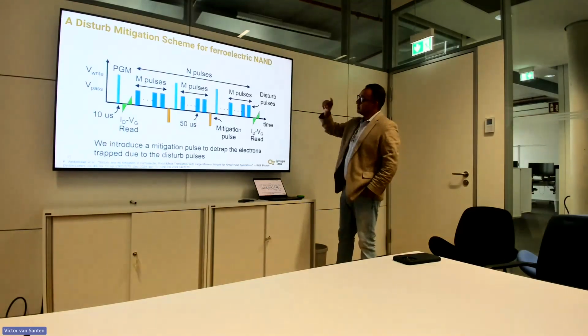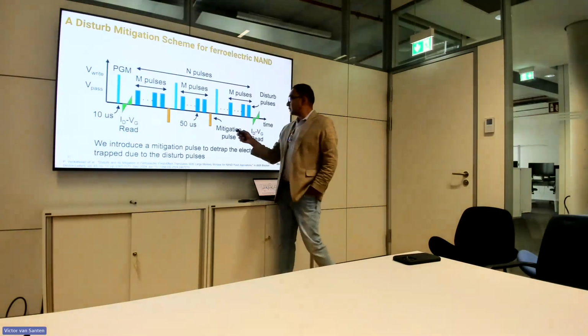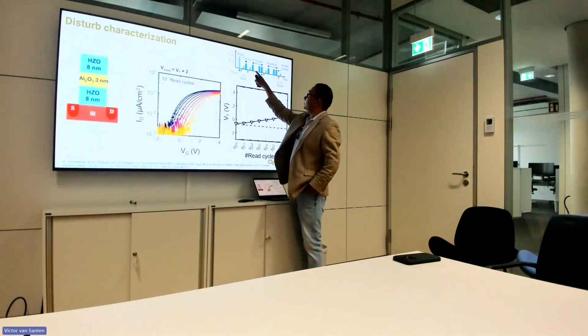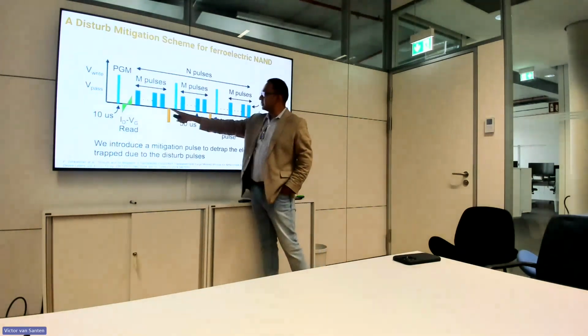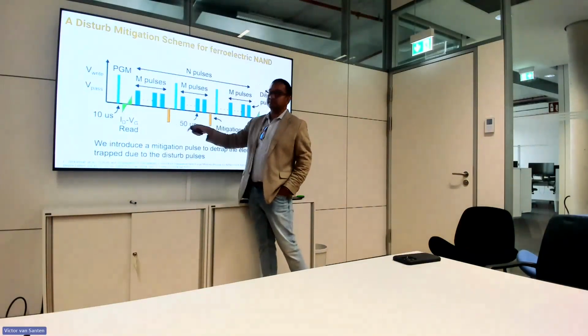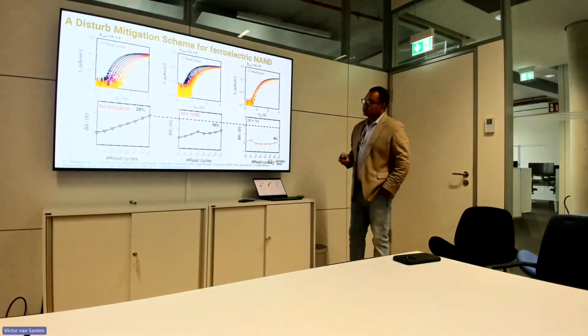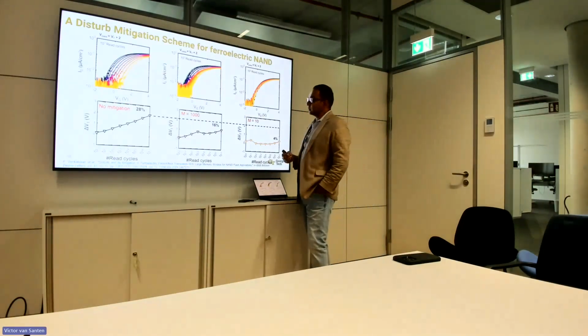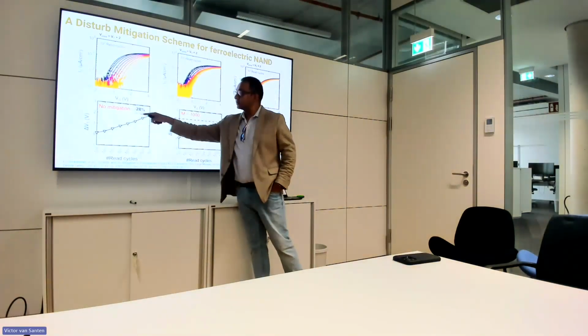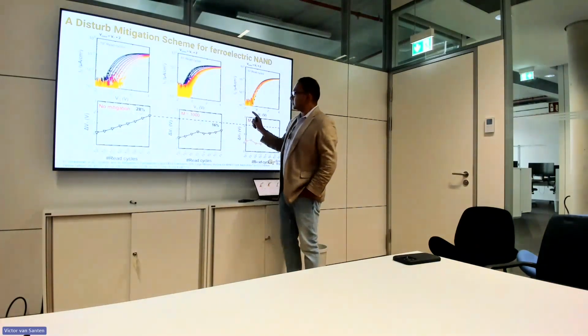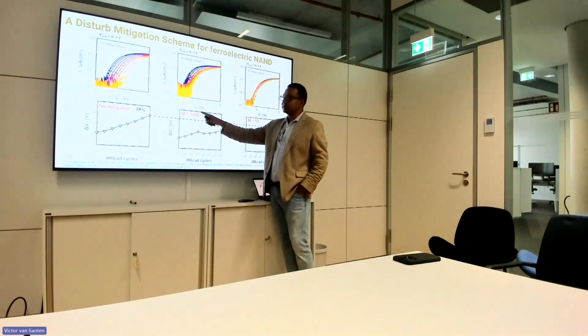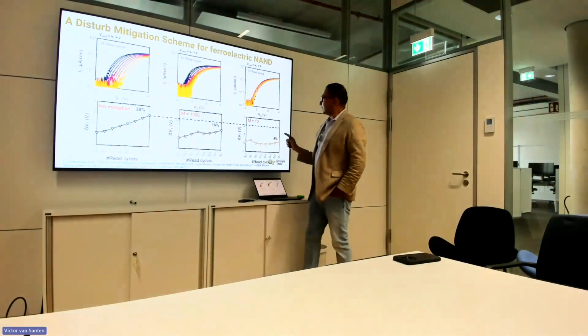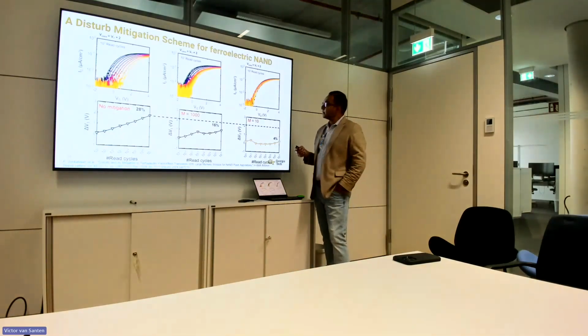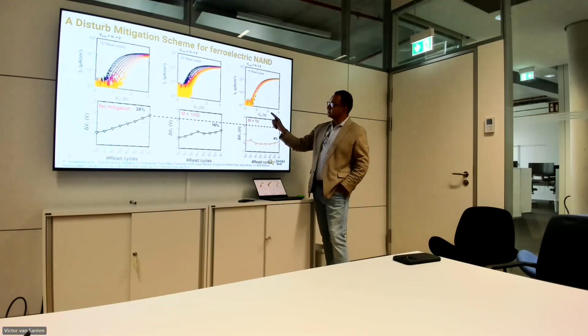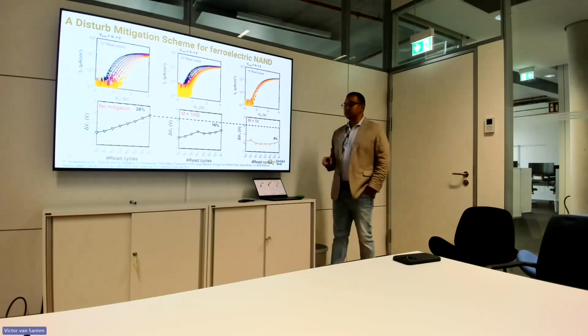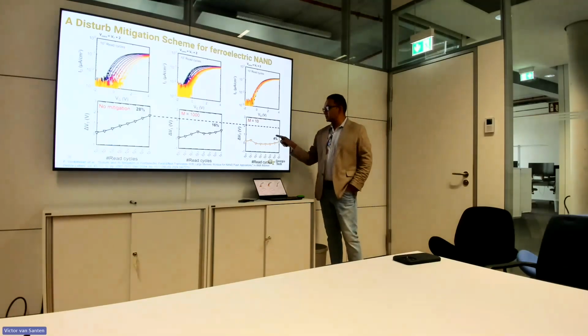So we also did a similar disturb mitigation scheme where in the previous case, we were applying all these pulses, but now what we're doing is that we are applying a negative pulse over here. Okay. And once we do that, we can clearly see that previously without any mitigation, there was 28% disturb, but now once we have this mitigation pulse after 80,000 cycles, it goes down to 16%. And in the extreme case, just for the sake of demonstration, if we have a smaller mitigation pulse, then we can actually reduce the disturb to 4%.